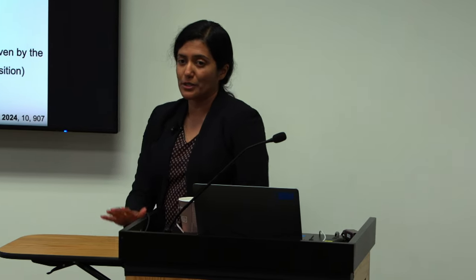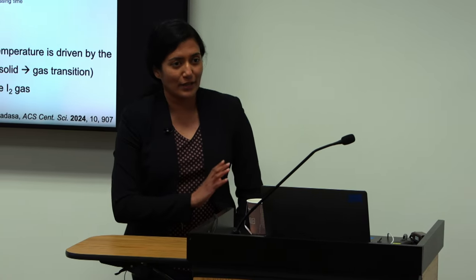And if you ask, why does this happen at room temperature? It's because the bonds that you must break are much weaker in the halide perovskites compared to the oxide perovskites. And for both oxide and halide perovskites, the entropy of this reaction is massive because you're going from a solid to a gas. This reaction is spontaneous at room temperature.